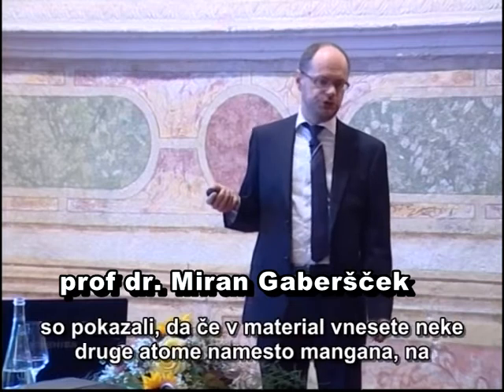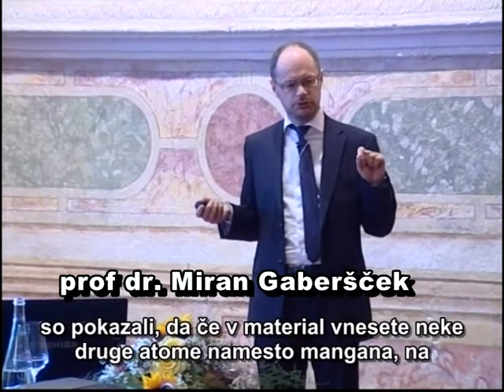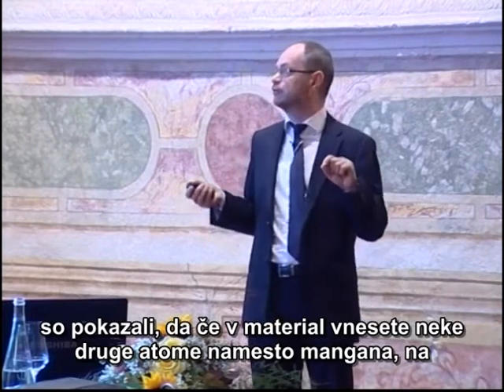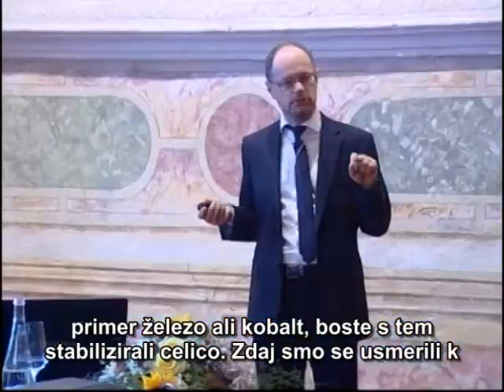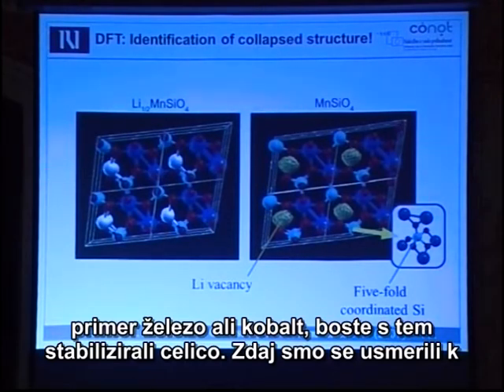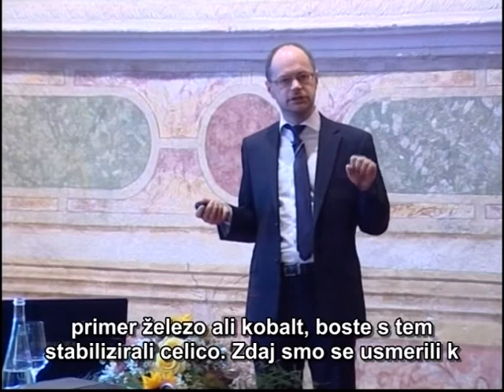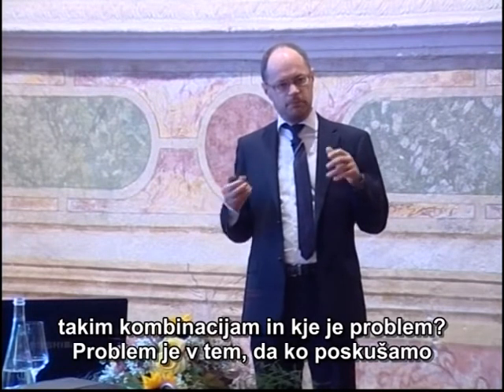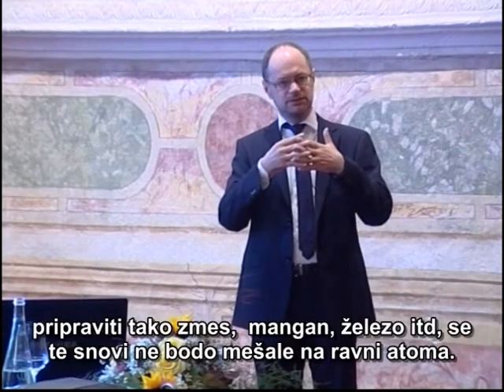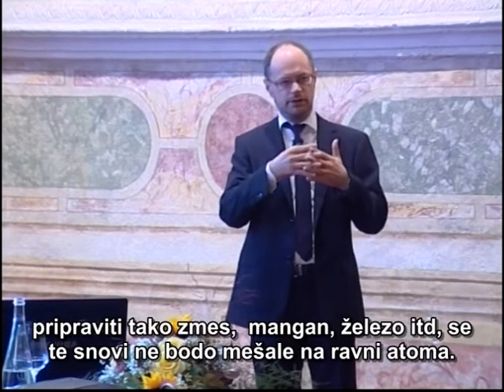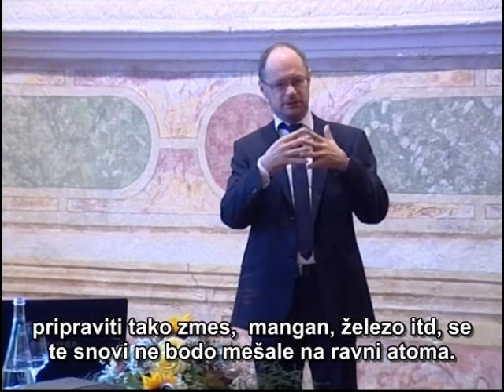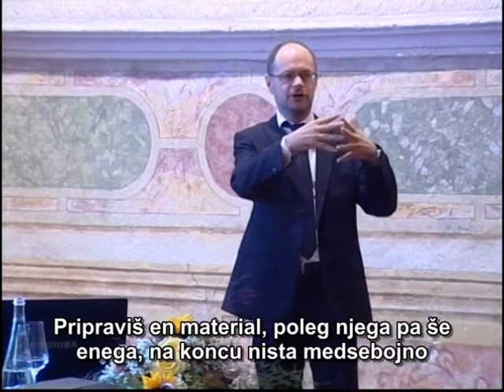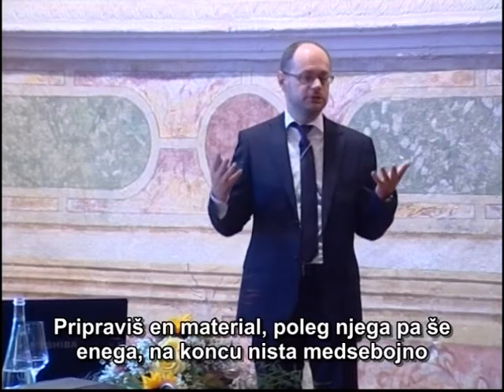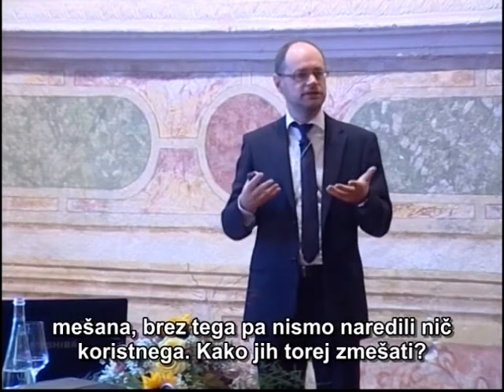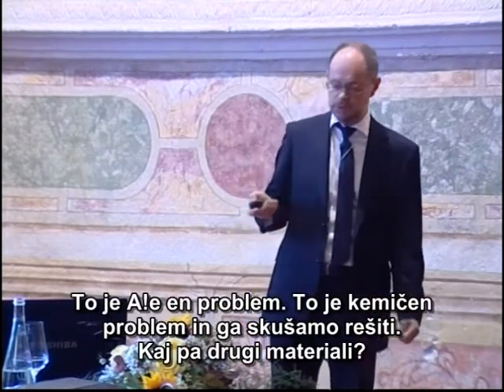The same type of calculation showed that if you dope, so if you put some other atoms instead of manganese, like iron or cobalt, you will stabilize the cell. And we are heading now towards these combinations. Where is the problem? The problem is that when you try to prepare such mixed ceramics, mixed manganese, iron, and so on, this will not mix. It's not mixed on the atomic level. You prepare one material, beside that another, they are not intermixed. So if they are not intermixed, you didn't do anything useful. So how to mix them? This is another problem. This is a chemical problem. We're trying to solve it.